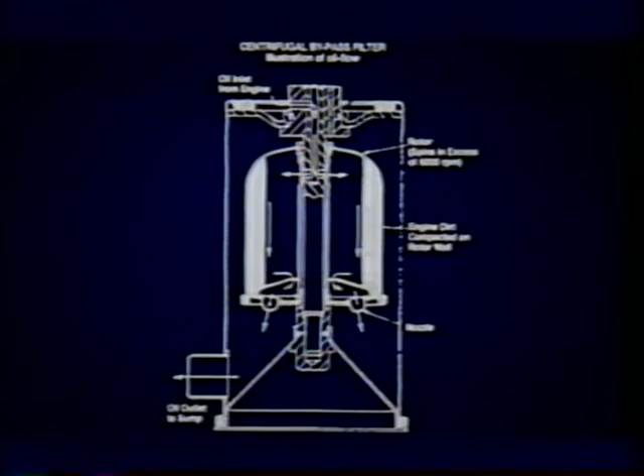The 3176 has a centrifugal bypass oil filter available as an option. The filter works by directing the bypass oil through a hollow centrifuge cartridge and out 2 opposed nozzles in the bottom. The oil pressure causes the cartridge to spin in excess of 6,000 RPM. Centrifugal force overcomes the force of the oil flow and removes the relatively heavier contaminants by holding them against the side of the spinning cartridge. After the disposable cartridge has trapped about 0.7 kilogram of contaminants in this way, it needs to be replaced.